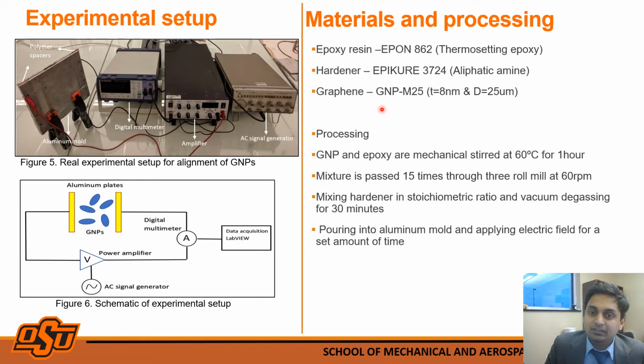Basically, the materials are epoxy, hardener, and graphene. The graphene and epoxy are mechanically stirred at 60 degrees for an hour, and the mixture is passed through a 3-roll mill, which breaks the agglomerates. Hardener is added in a stoichiometric ratio, and the mixture is poured into an aluminum mold and an electric field is applied for a set amount of time.